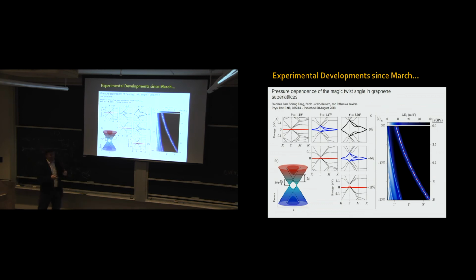So we calculated what pressure you need to apply to convert a given angle into a magic angle. For example, 1.12 degrees is magic, has flat bands at ambient pressure. 1.47 is not magic, the bands disperse. You apply a certain amount of pressure, it becomes flat. At 2 degrees, not magic, apply a bit of pressure, apply more, it becomes flat. So we calculated the pressure dependence of the magic angle condition.